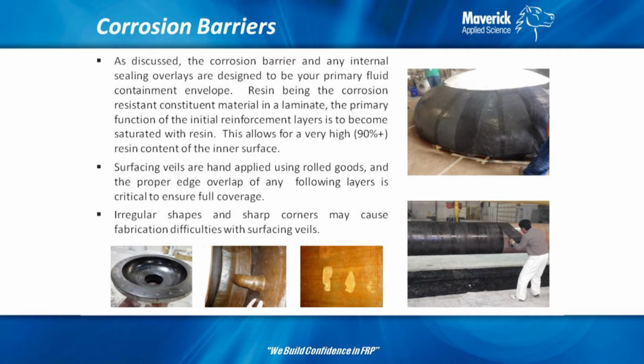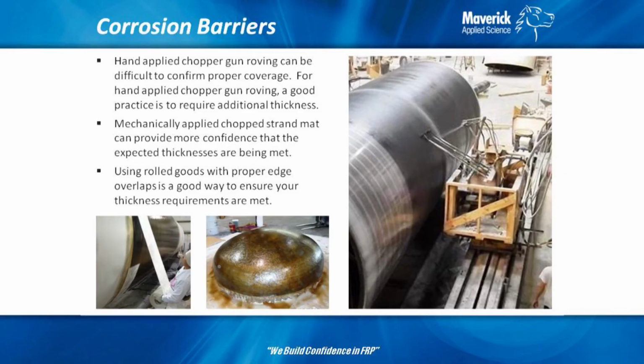But as you build a flange, or you weld the neck of a dip tube or something in, some of these veils are much more difficult to work with as a fabricator. So even though you think you're doing a good thing by using carbon veil, if your fabricator is not well versed in carbon veil, you may not get a good part anyway. You may end up shooting yourself in the foot a little bit.